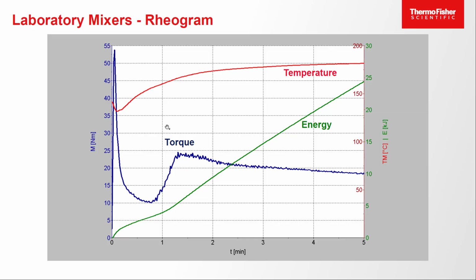And that continues with an increase in viscosity until it comes to a maximum. This is our second peak in the curve, and this is where we have a fully developed melt of a fused material. Now, due to additional shear we put into a sample, because the rotors are still running, the temperature is still rising until it comes to a steady state. And together with that, also our torque signal first goes down a bit and then comes to a steady state. You can say the torque at the end of this curve is a relative value of the melt viscosity of a sample.